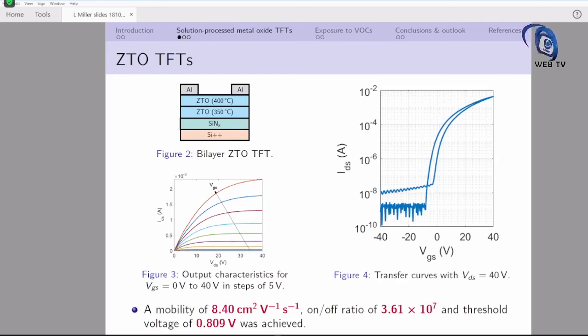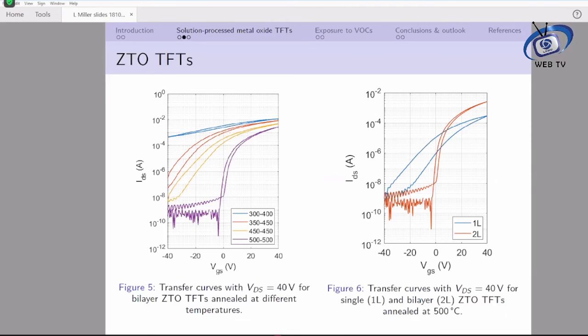This slide summarizes the work conducted by my group on bilayer ZTO thin film transistors. The effect of increasing the number of active layers and annealing temperature on electrical performance is demonstrated. In Figure 5, 300-400 denotes that the first layer was annealed at 300 degrees Celsius, and the second layer was annealed at 400 degrees Celsius. You can see that threshold voltage or turn-on voltage is dramatically reduced, and mobility is increased after both layers are annealed at higher temperatures. This may have been owing to a greater proportion of metal oxide metal bonds, which created a highly ordered lattice and therefore greater crystallinity to facilitate charge transport.